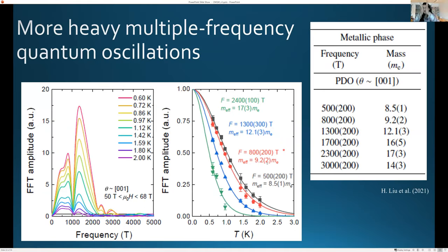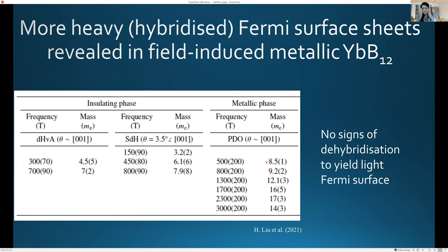There's a bit in between we can't access because everything is changing non-monotonically. But on the left, at lower fields where it's insulating, you see low frequencies and high masses. Then there's a small gap in field. And then beyond that field, you get much larger amplitude quantum oscillations. Those have a few overlapping frequencies with similarly high masses, but also higher frequencies with higher electron masses.